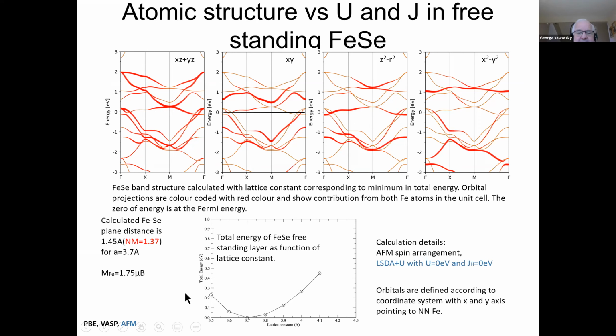It's 1.7 Bohr magnetons. That's what you get if you look at the minimized density functional distance of 3.7 angstroms for the lattice constant, 2 atoms per unit cell, 2 irons. Okay, and by the way, the distance of the selenium to the iron plane now is 1.45 angstroms, whereas in the non-magnetic case, it was 1.37. So this shows you exactly this effect of the elongation of that bond simply because you're occupying antibonding orbitals.